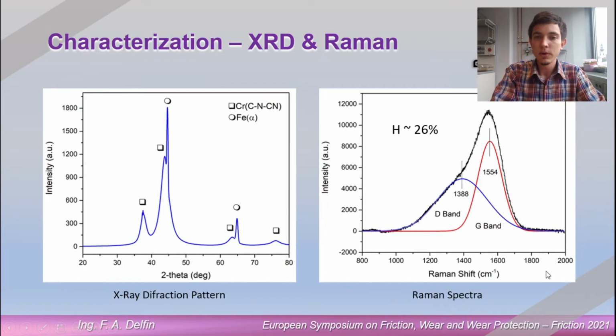So here we have more characterization. We did the XRD of the samples. Of course, you cannot see the DLC coating in the XRD because it's amorphous, but you can see the peaks of the iron here and also all the peaks of the chromium compounds, chromium carbides, nitrides and carbonitrides. The problem is they share pretty much all the peaks and you need to do further investigation to differentiate them. So we don't know exactly which one of them are there, but they are there.